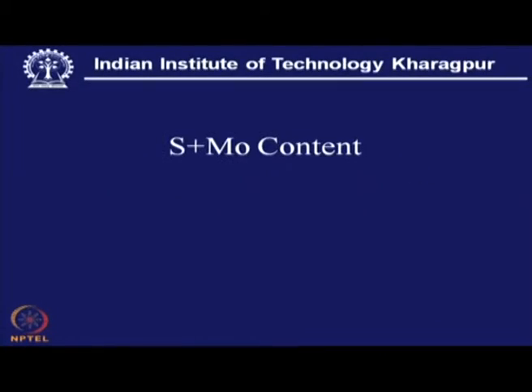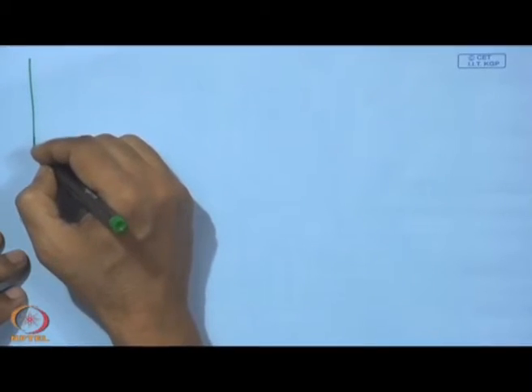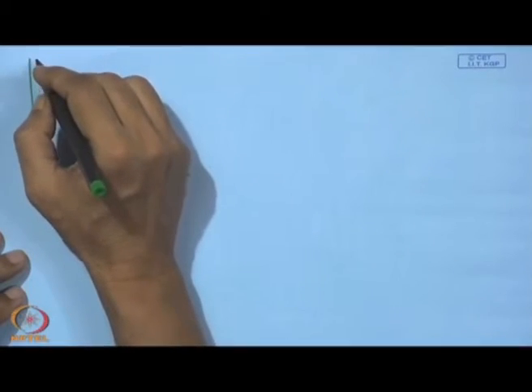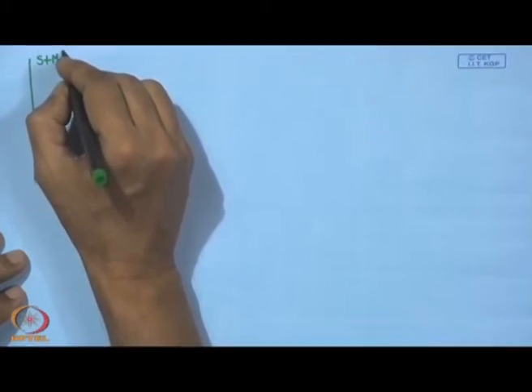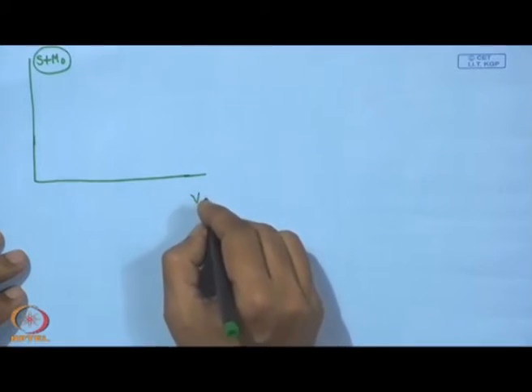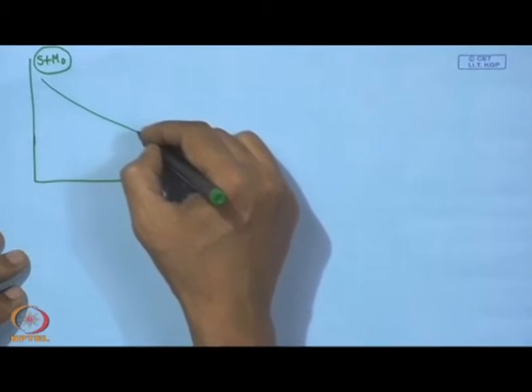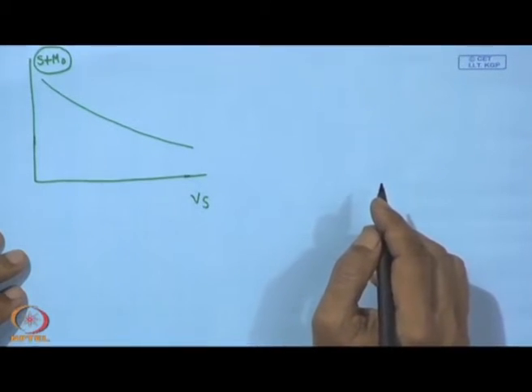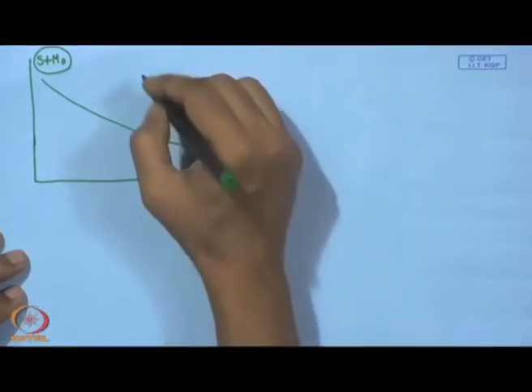So, these are the two things one can immediately look into, apart from the coefficient of friction and also the wear coefficient. So, we can look into this effect of substrate bias. Now, with this increase of substrate bias, what we can see is that the Mo plus S content, that means what we are interested in, sulfur plus molybdenum in the coating, with this increase of bias voltage shows a falling curve, and this is because of the re-sputtering of molybdenum MoSx.